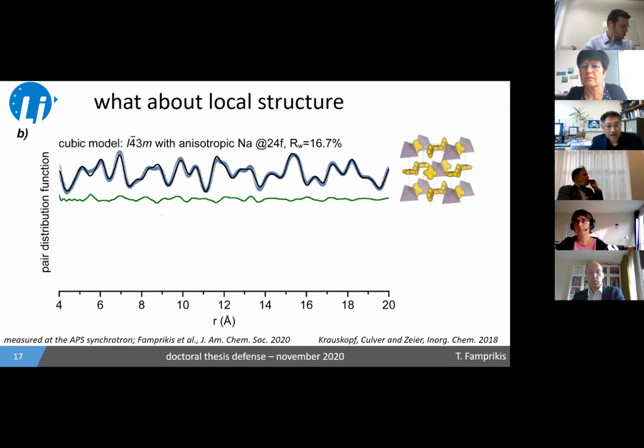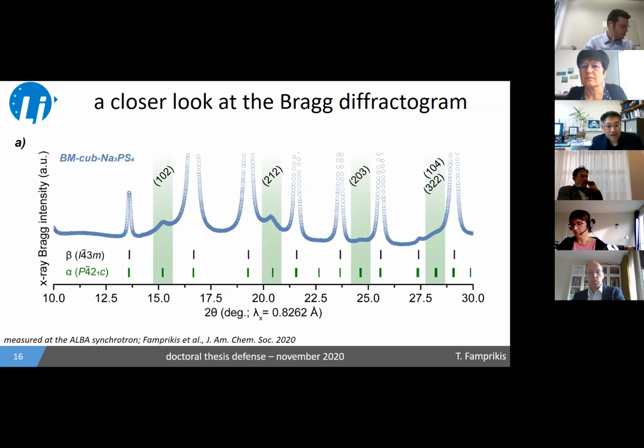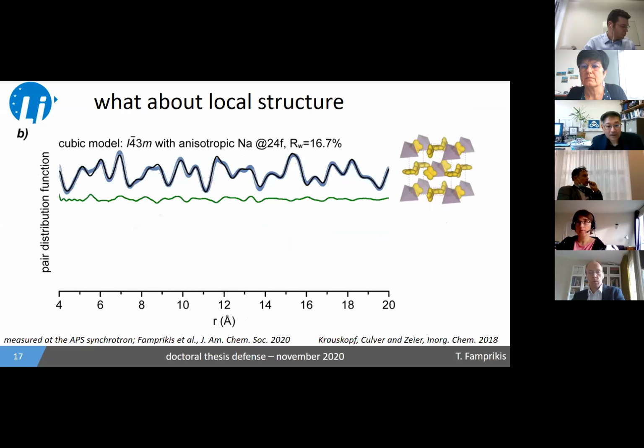So basically what we can do from here is try and investigate more locally what the structure looks like by taking a diffractogram like this and performing a Fourier transform to bring it from Q space, inverse space, into real space. So this is what's called the pair distribution function, as shown here. So we have a real distance on the x-axis, and each peak here basically corresponds to the distance between two different atoms in the material. So we try to fit to the cubic model in agreement with the Bragg interpretation. And you can see that we get something close, but there's still some residual difference.